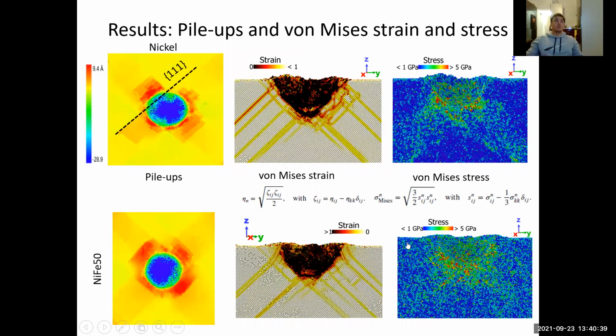What else can we do with the MD simulations and the experiments? I was talking about the pile-ups and also the slip systems. Now for nickel, this is how the pile-ups look when you reach the maximum indentation depth. And in this line, I'm making sure that this is the slip system. And then you can see the geometry of the pile-ups. All of these are the atoms that are accumulated above the surface.